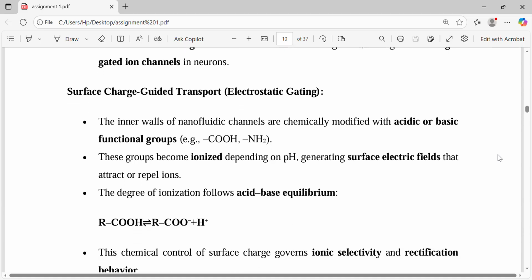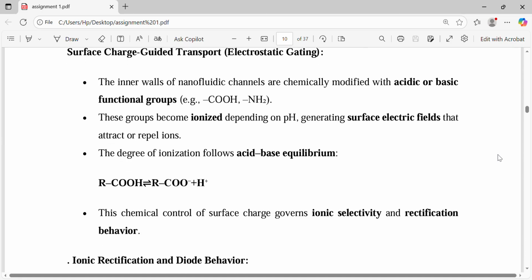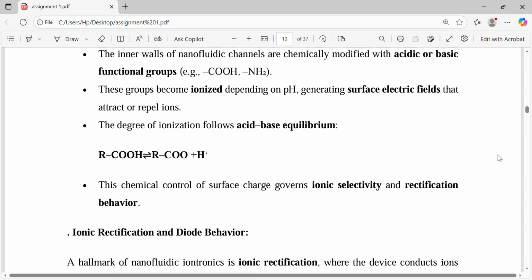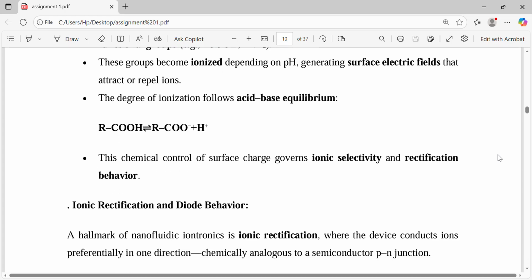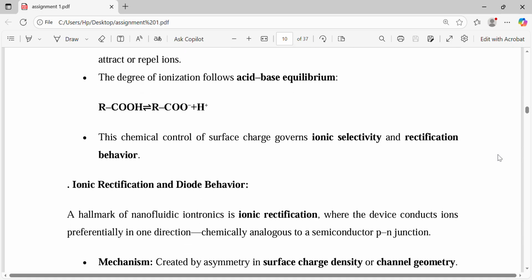Surface charge guided transport, electrostatic gating. The inner walls of nanofluidic channels are chemically modified with acidic or basic functional groups. These groups become ionized depending on pH, generating surface electric fields that attract or repel ions. The degree of ionization follows acid-base equilibrium: R-COOH equilibrium with R-COO negative plus H positive. This chemical control of surface charge governs ionic selectivity and rectification behavior.